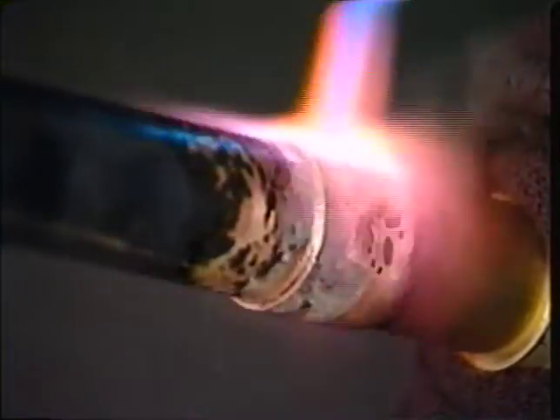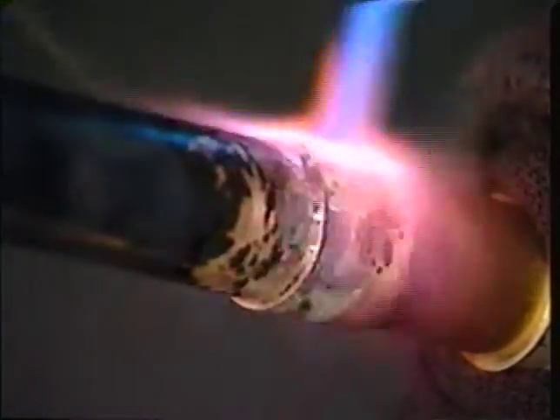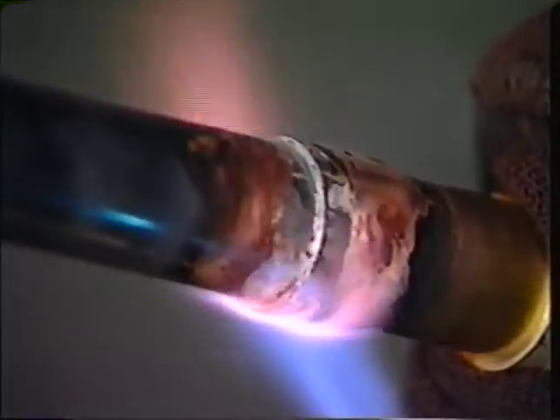If the metal is hot enough, the alloy will flow. Move the rod around the circumference of the joint while still applying heat to the female. The alloy is drawn into the joint by a process called capillary action. Heat on the female helps promote this flow. This powerful force can overcome gravity and will draw the filler metal into a joint even if it is upside down. To work, however, the parts to be joined must have proper fit and clearance and be clean.